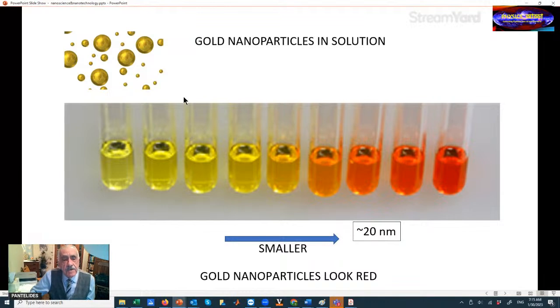One of the key elements of nanoscience, of nanoparticles, is an example here of gold nanoparticles. If they are fairly large, you see the gold color if you have them in a solution that is otherwise clear. You put the nanoparticles in there, you see a nice gold color. But if the nanoparticles are smaller, 20 nanometers or less, their color changes to red. Obviously, something is happening in the world of nanoparticles.